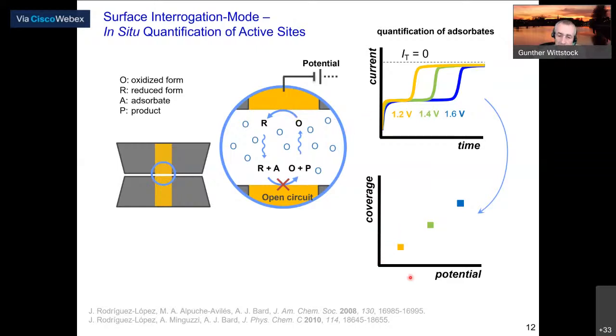So then we can make experiments like this. We pose our sample at a certain potential here. Then we make such a titration curve. We integrate, we determine the charge by integration and calculate a little bit further, get the coverage. Then we make the next experiment by which we extend the potential excursion to a higher value. So we form a little bit more oxide, we titrate it, you see the charge under the curve will become larger, and we go on like this, and then we can make relations between coverage and potential.